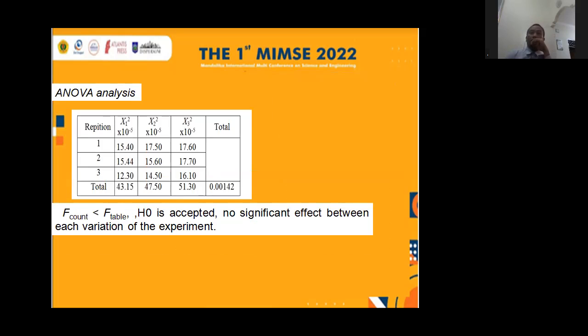By ANOVA analysis, we would like to validate the experiment using a theoretical analysis. In this case, we use one-way ANOVA. We have the rule that if F count is less than F table, it means H0 is accepted. It means also there is no significant effect between each variation of the experiment. Oppositely, if F count is more than F table, H1 is accepted, H0 is not accepted, and so there is a significant effect between each variation of the experiment.